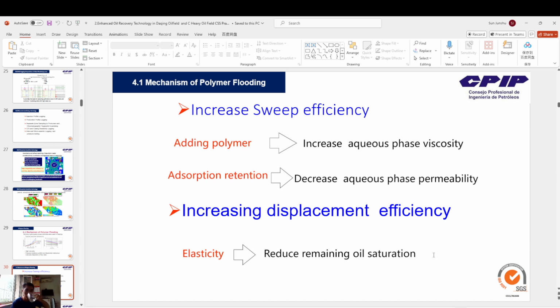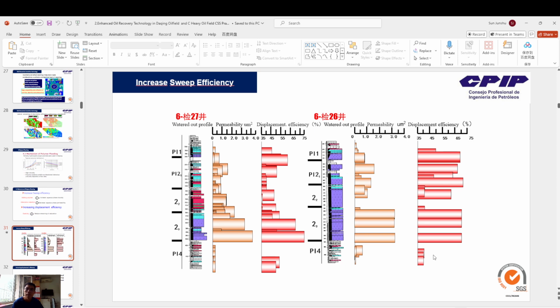Mechanism of polymer flooding. First, increase sweep efficiency. Adding polymer can increase the aqueous phase viscosity, adsorption and retention, decrease aqueous phase permeability, increase displacement efficiency, elasticity, and reduce remaining oil saturation. It can also increase sweep efficiency.